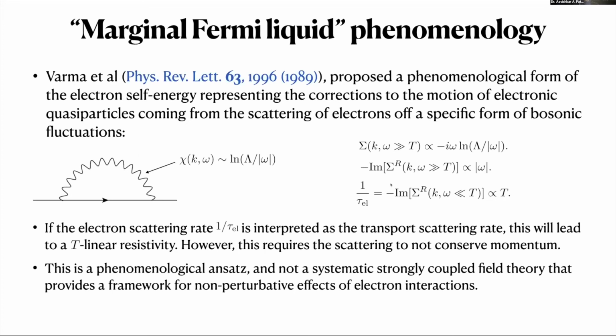So one phenomenological construction that has existed for a long time is a marginal Fermi liquid, where if the bosonic susceptibility has this local form, it doesn't depend on space, but only depends on time or frequency, with the log singularity that gives a single particle electron scattering rate that's proportional to temperature at a finite temperature. But this of course is not the transport scattering rate, it's the one particle decay rate.